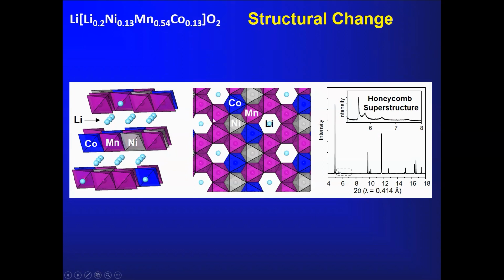This is the plan view, if you like, of a transition metal layer. And if you remember in X-ray diffraction, there is virtually no difference in the scattering between cobalt, manganese, and nickel. So all of these will look similar. You can see that this is a very nice honeycomb structure. This is the lithium here. It's the classic honeycomb superstructure that one sees in most of these lithium-rich compounds. And on the right, you see a powder diffraction pattern for this material. And here's the expanded region in this rectangle. And these are the superstructure peaks. And you can assign these peaks to this honeycomb superstructure. So this is just experimental evidence showing you that you have this nice hexagonal superstructure.